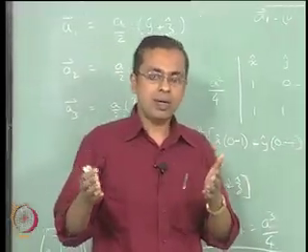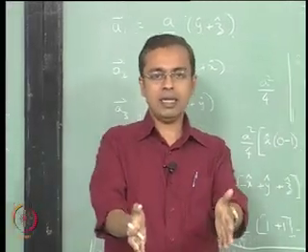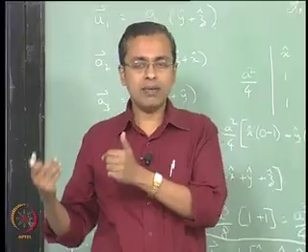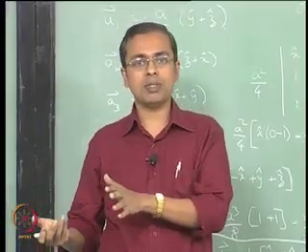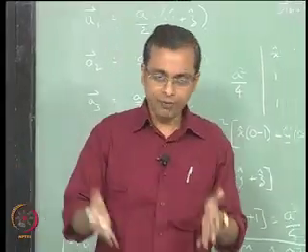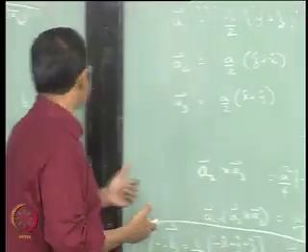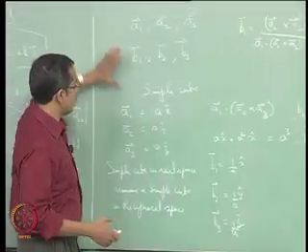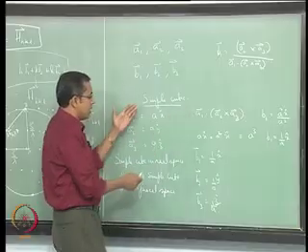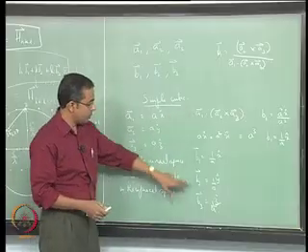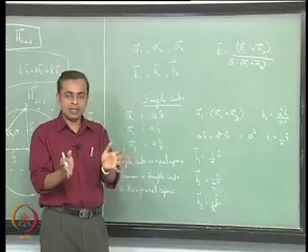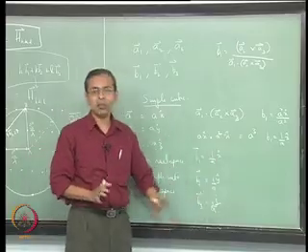Now we also want to understand that if you are given a real material with a certain crystal structure, how will you represent that structure in reciprocal space, so that you can see the diffraction process there. We find that if our original structure is simple cubic, then its reciprocal lattice, the B1, B2 and B3 that we calculate, is still simple cubic in geometry.